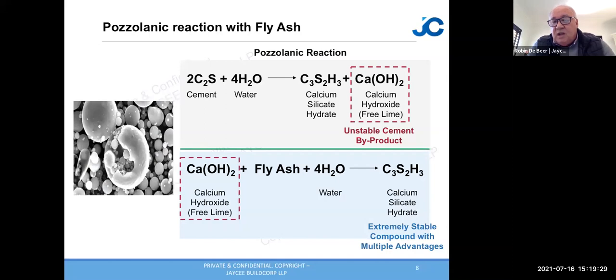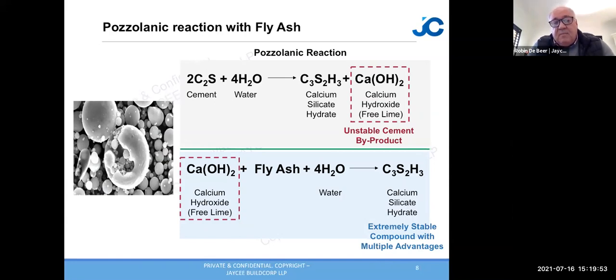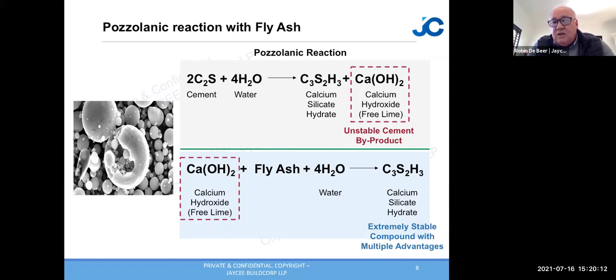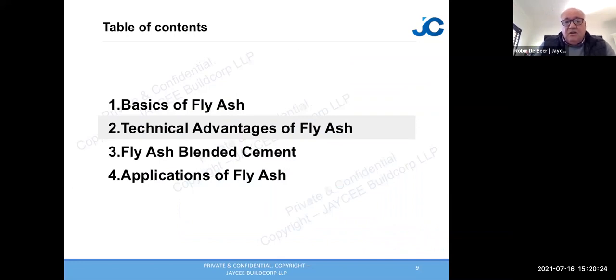When you add cement and water together you get calcium silicate hydrate, but you also get calcium hydroxide — an unstable free lime. This free lime then reacts with water and fly ash to give you more calcium silicate hydrates, which is the two-stage cementing action. The cement sets up at three to seven days, and then from seven days onward the free lime reacts with fly ash, filling in any remaining areas and making the concrete matrix very fine, giving long durability.